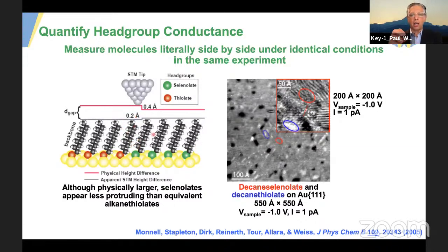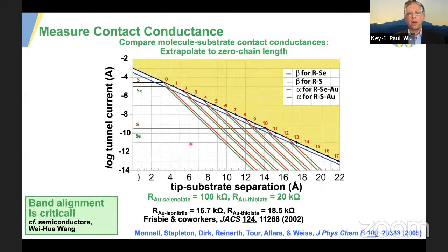And our STM tip height, remember, is a proxy for the conductance. So if the tip has to go closer, that means these molecules are less conductive. And then again, we did many different combinations. And we extended down to 0 chain length and showed that indeed for these backbones, the thiol is 5 times more conductive than the selenol connection.